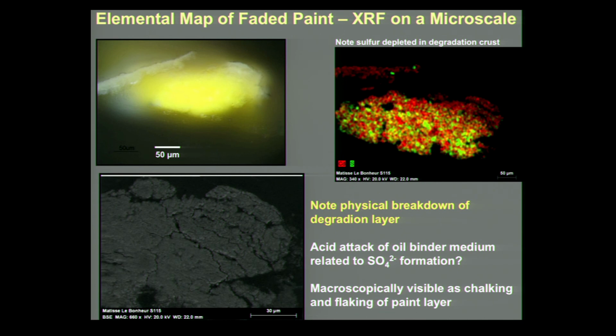We can also do an elemental map of the faded paint, sort of like X-ray fluorescence on a microscale, and each of the green data points here represents a sulfur data point, and each of the red data points represents the presence of cadmium. And you can see that cadmium is present throughout the paint layer, but that sulfur is being lost at the surface of the paint layer.